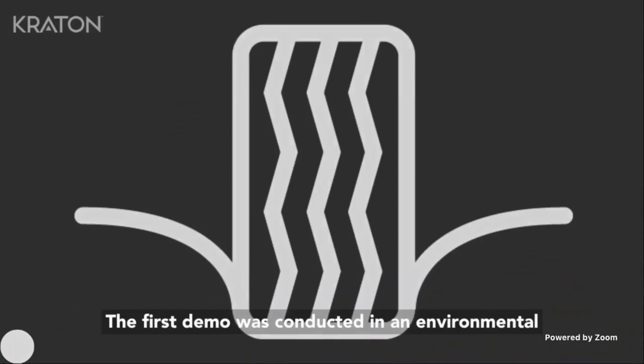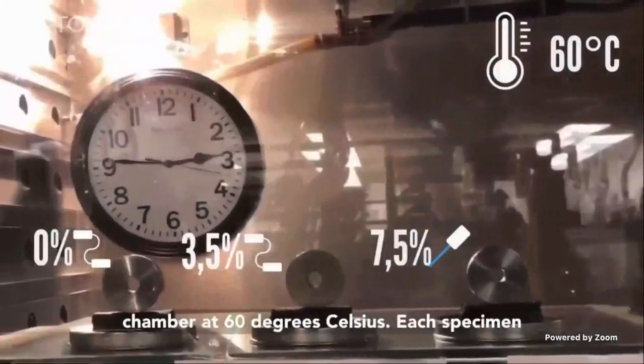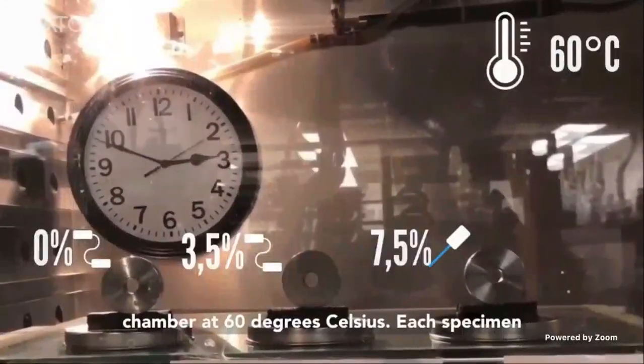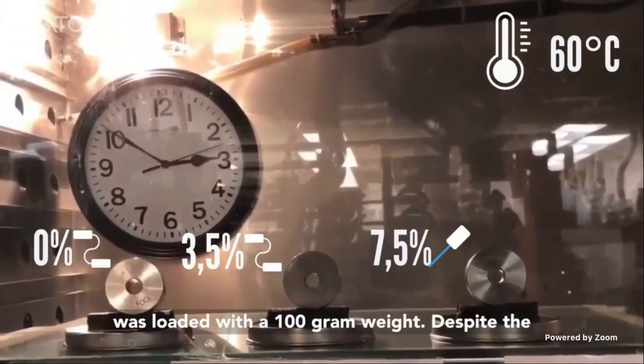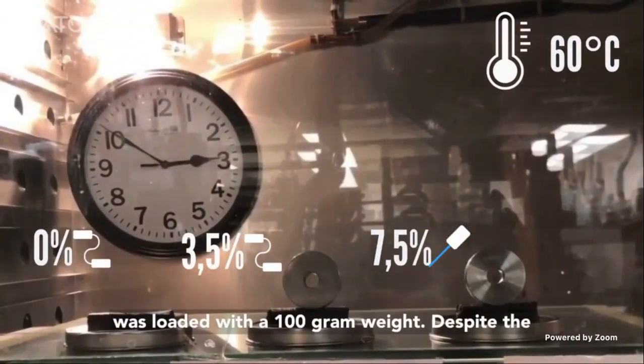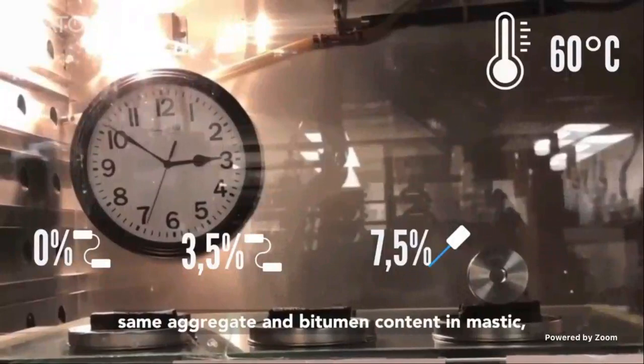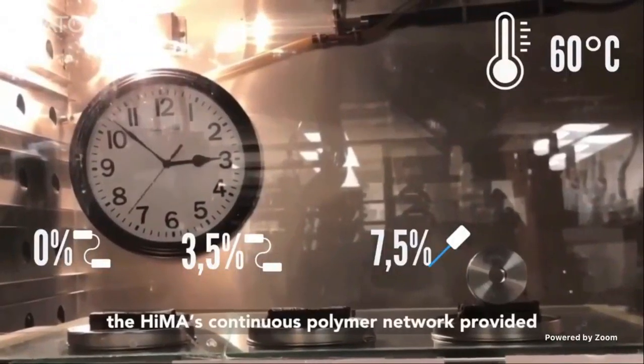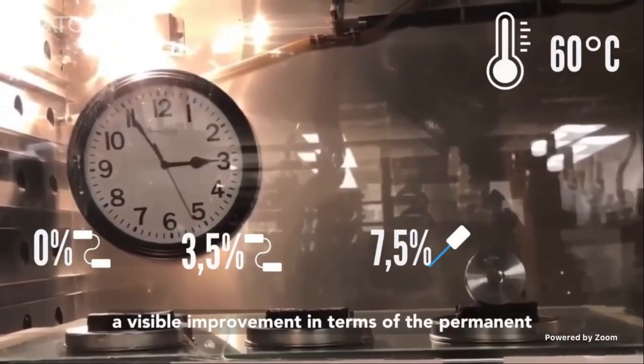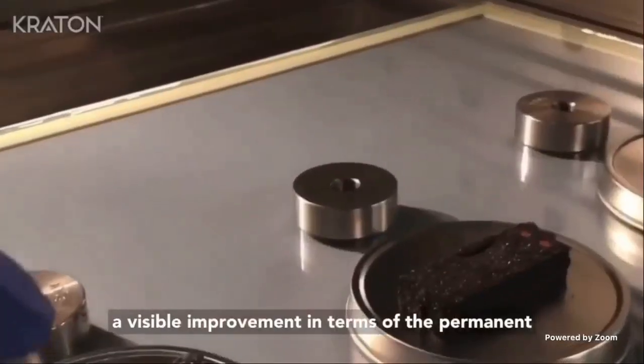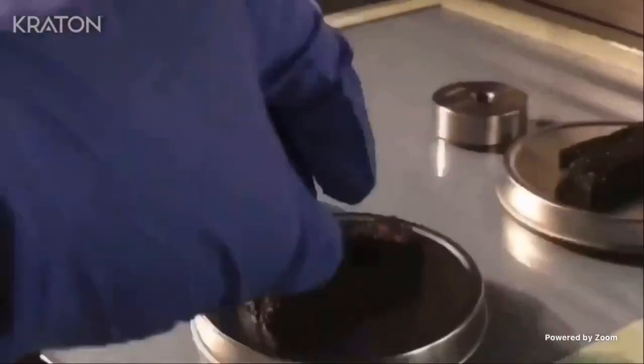The first demo was conducted in an environmental chamber at 60 degrees Celsius. Each specimen was loaded with 100-gram weight. Despite the same aggregate and bitumen content in mastic, Kraton's continuous polymer network provided a visible improvement in terms of the permanent deformation resistance.